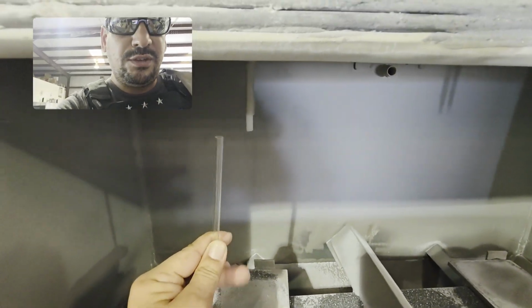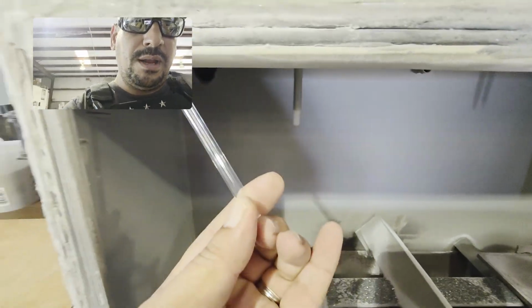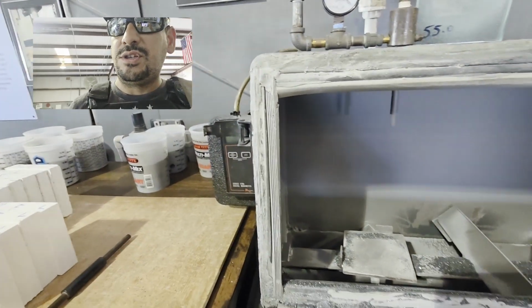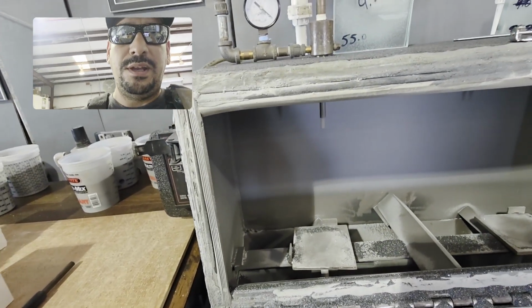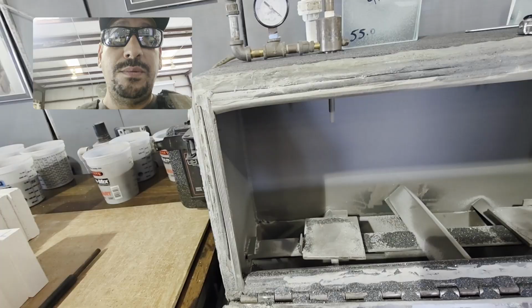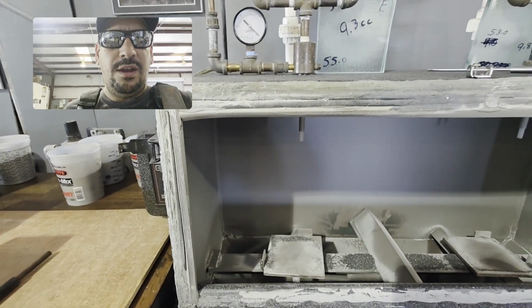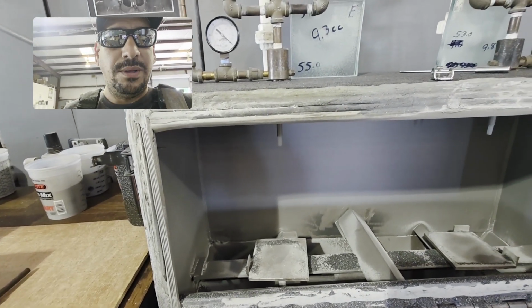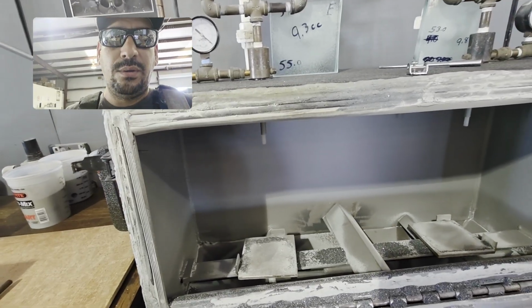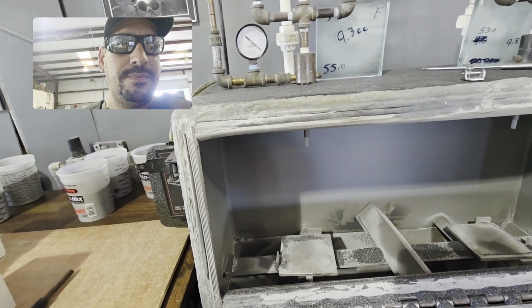So 8 inches from the specimen to the bottom of this tube is the correct measurement for C704, not to be confused with any other measurements, because 8 inches is very, very close to another measurement that we use in here. So remember, 8 inches is for abrasion resistance.